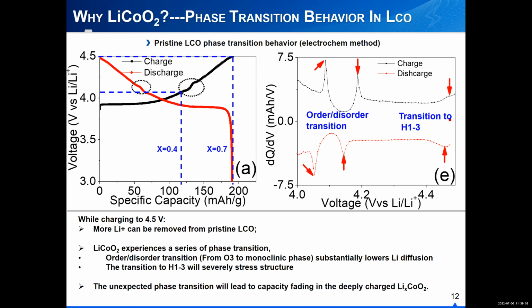Why? The higher the capacity, but when we charge the lithium cobalt oxide to high voltage, this material will experience a series of phase transitions. The first one is the order-disorder transition right here. The order-disorder transition will substantially lower the lithium ion diffusion. And when we try to charge higher, the transition to the H1-3 phase right here will seriously stress the structure. So these two unexpected phase transitions will cause the capacity fading in deep-charged lithium cobalt oxide. That's why when lithium cobalt oxide was first introduced into the market, it was strictly limited to 4.2 volt. They just try to avoid these two kinds of phase transition.